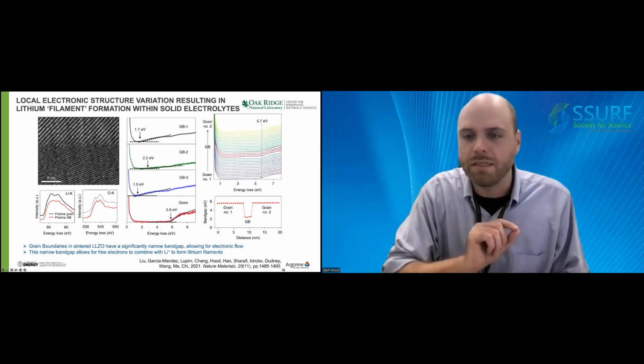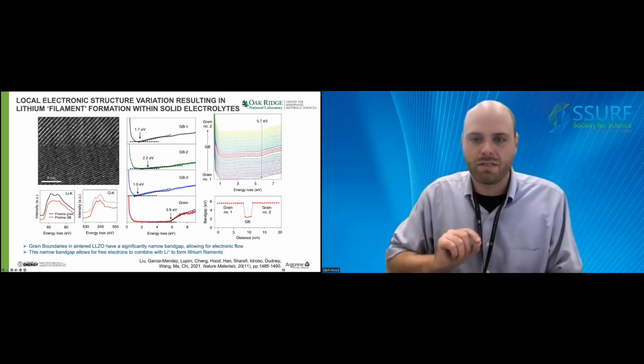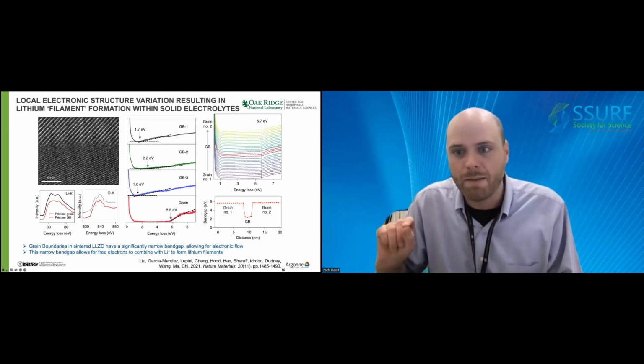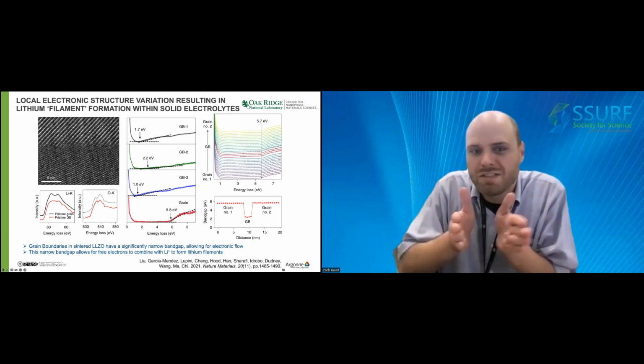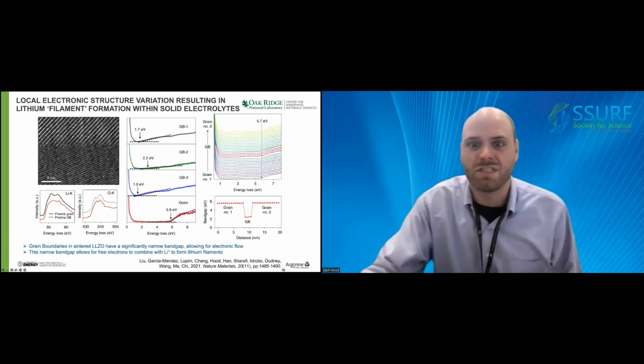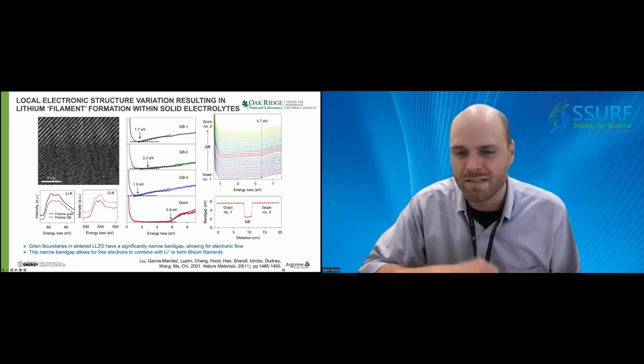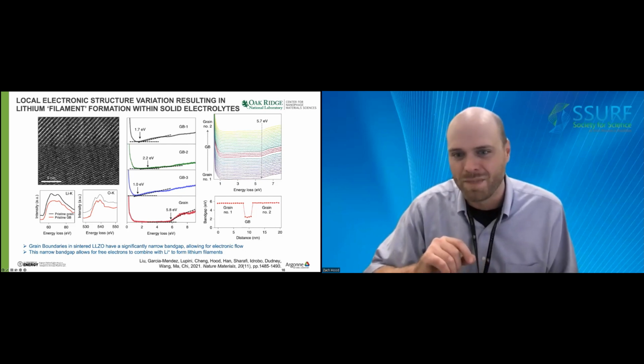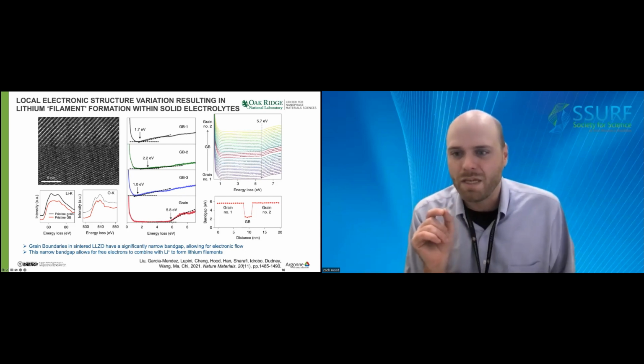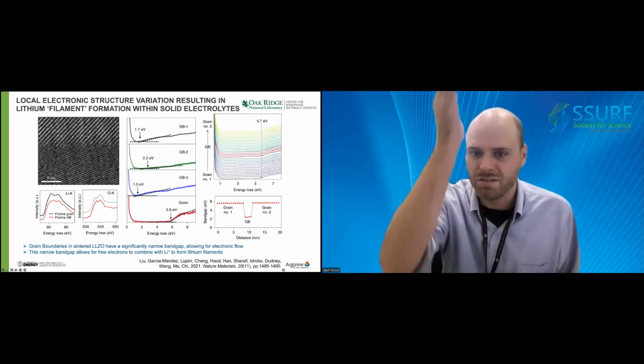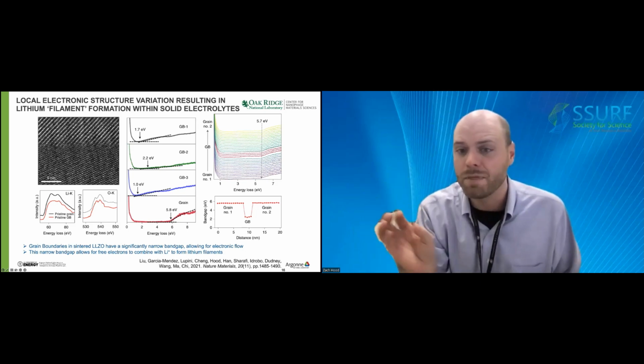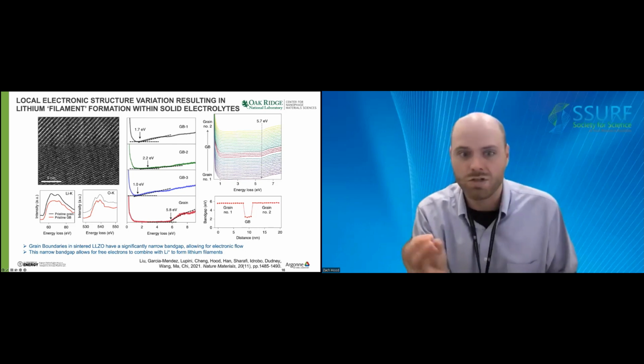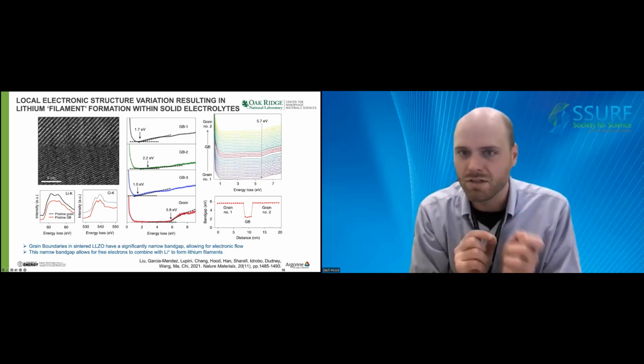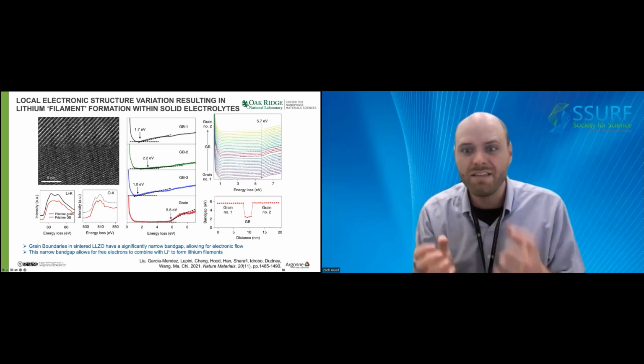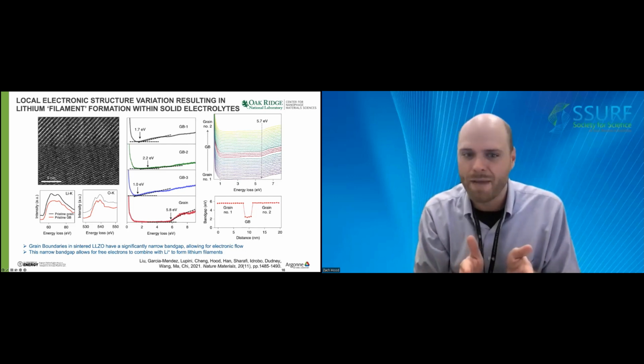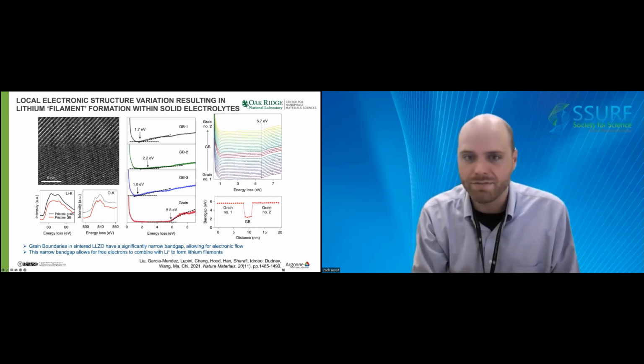However, at the grain boundary, valence band electron energy loss spectroscopy revealed that the band gap was drastically reduced to around 1 to 2 eV, which is reminiscent of a semiconductor. And this is not what we want necessarily in a solid-state battery. So this difference in the band gap can cause a flow of electrons into the grain boundaries, and it can potentially even cause the nucleation and propagation of lithium filaments within our solid-state electrolytes. These lithium filaments are known to short circuit a battery, which can then cause battery failure.